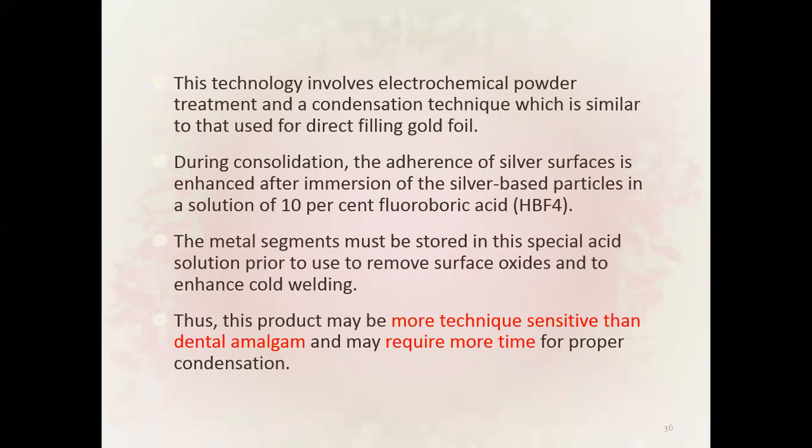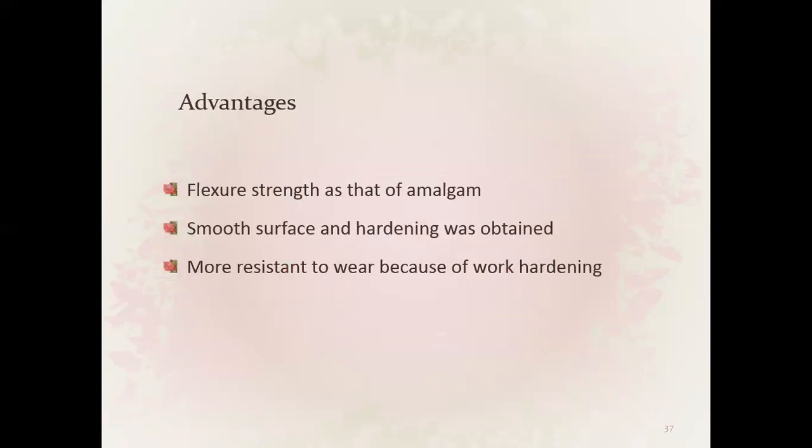The metal segments must be stored in a special acid solution prior to use to remove surface oxides and to enhance cold welding. Thus, this product may be more technique sensitive than dental amalgam and may require more time for proper condensation. Advantages: flexural strength same as that of amalgam, smooth surface and hardening was obtained, more resistant to wear because of work hardening.